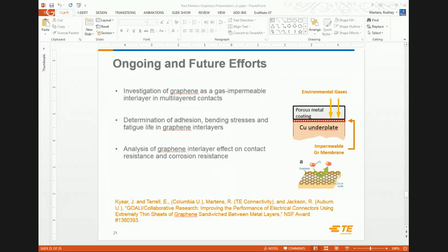Sure. As I mentioned, this is really, really early work. We don't have any plans to put this in a product. The biggest barriers for productizing this from our perspective come down to time and temperature. When we electroplate contacts in a normal environment, the strip is going through the plating line on the order of tens of meters per minute. And if you look back at the growth recipe, we're operating on the order of 10 hours. So first of all, there's a wild discrepancy on the time.